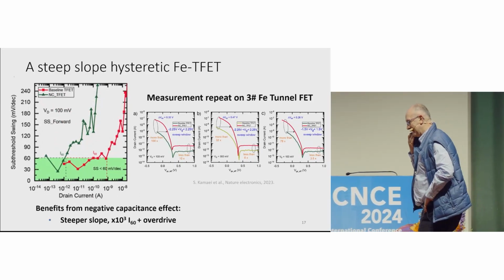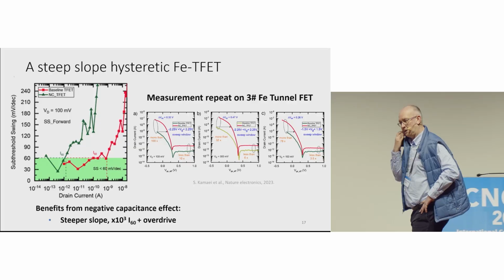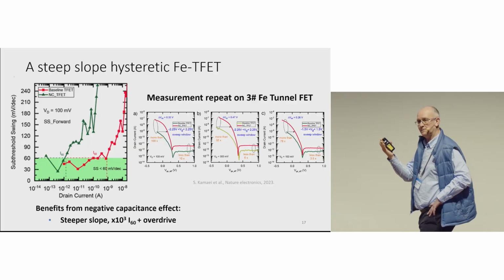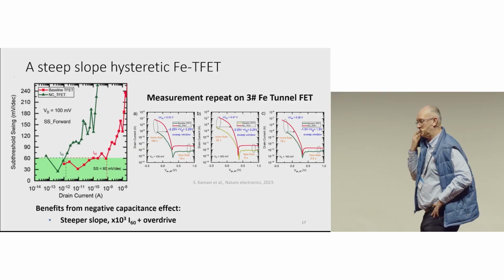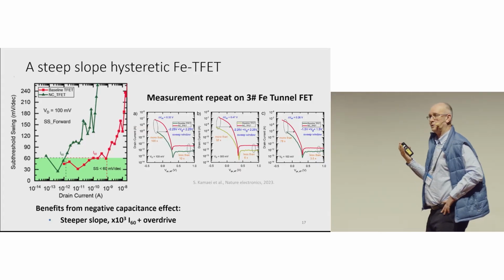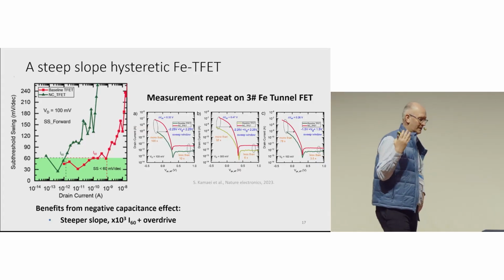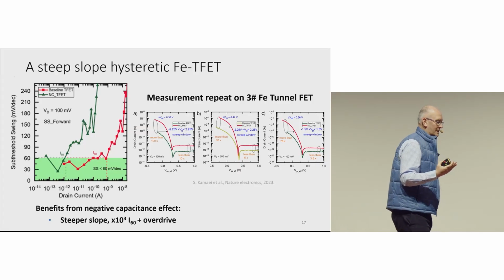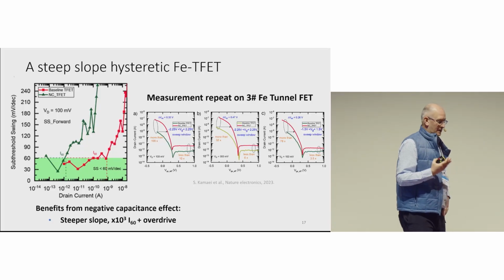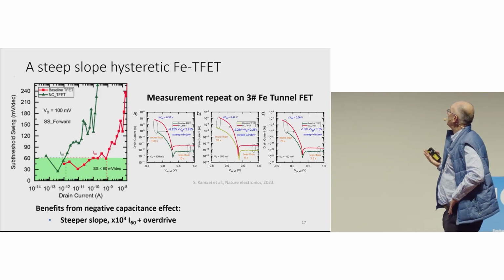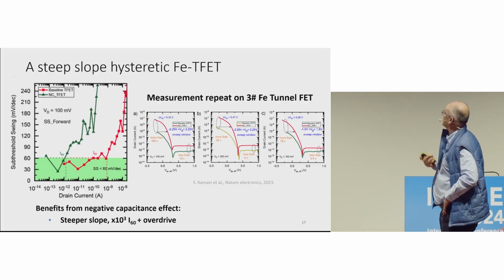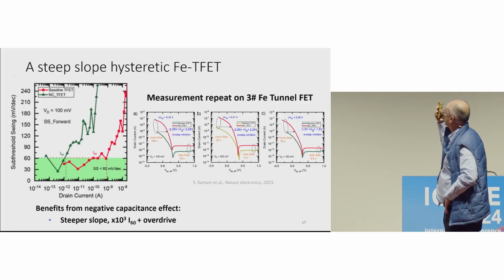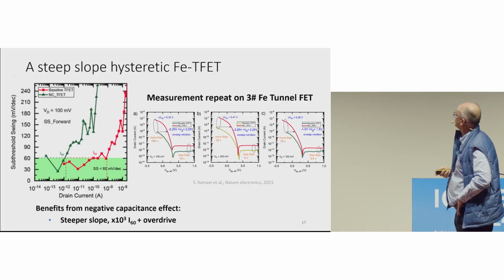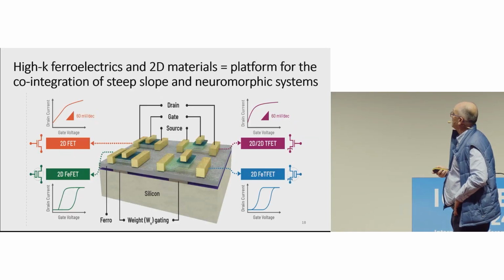And here, important maybe for the PhD: of course, you may have one experiment of this kind that looks very interesting, but we always ask our students to repeat it and to show, is this repeatable? Repeatable as performance, as behavior. So we try to do this on multiple devices and see the variability, because otherwise you'll never convince industry. Here there are 3 of these devices where this effect has been demonstrated.